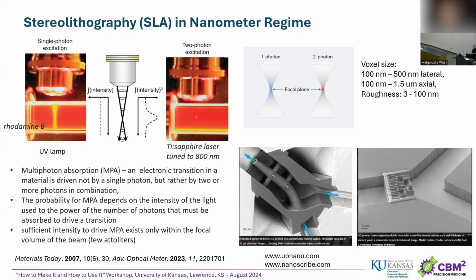It uses so-called 2-photon polymerization, and it comes from the fact that with what we saw in previous examples, it's 1 photon. You really polymerize a lot of resin. Even if you focus your laser or your UV light, polymerization will occur in a relatively large volume. So you have a larger volume of material being polymerized on one side.